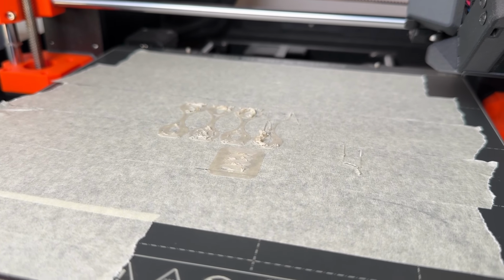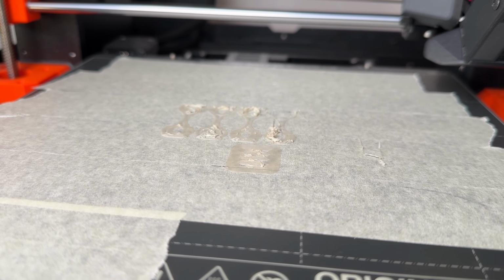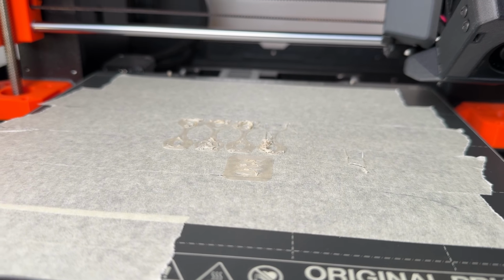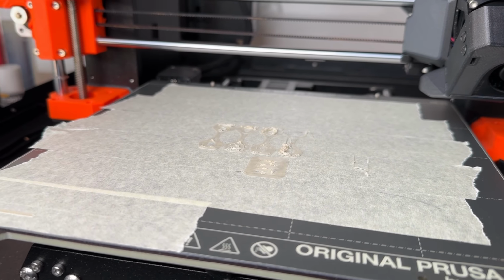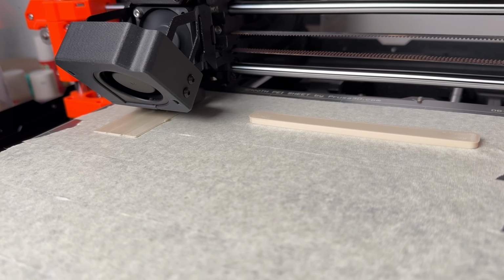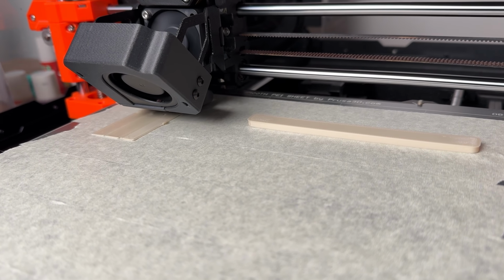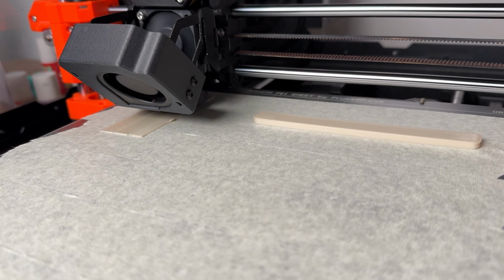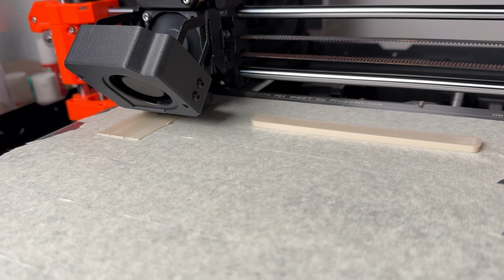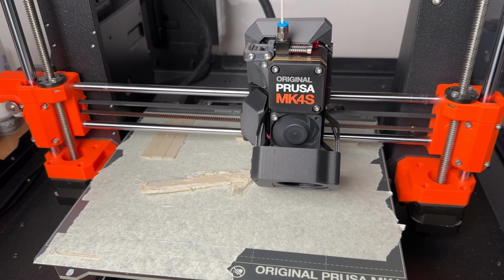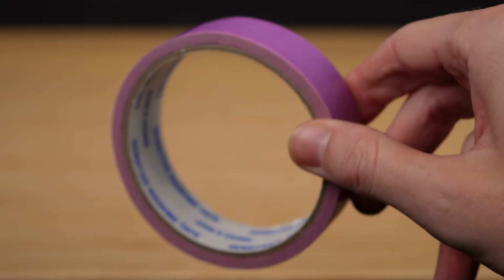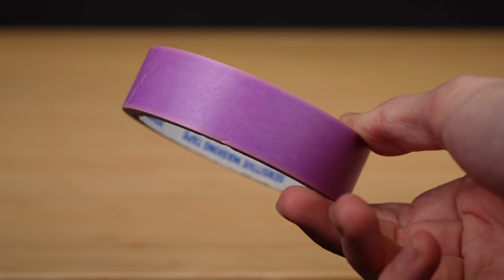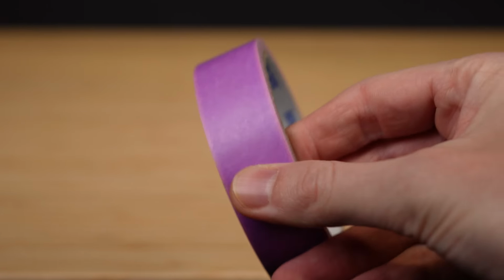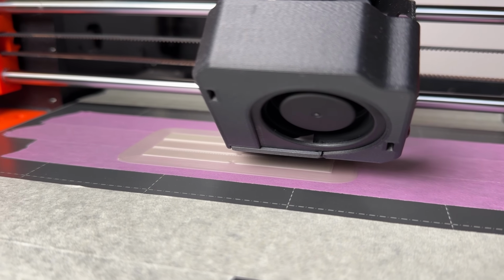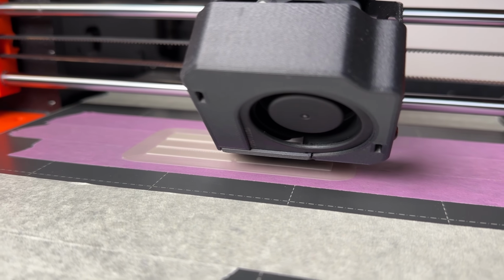My first G-code somehow messed up my filament settings. Well, that's how it looks when your PHA doesn't stick properly. With the correct settings and a cool bed, I restarted the print using the sequential printing feature where the printer completes each individual object. Parts still warped, so I decided to go with purple tape. It has a smoother surface and seems to be similar to frog tape. With the purple tape, parts stuck really well and my adhesion issues were gone.